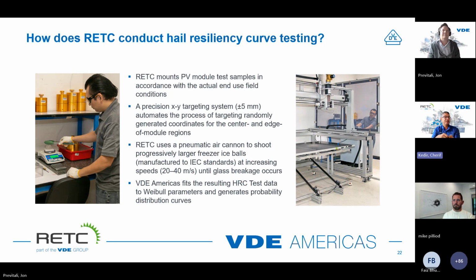And we do that, as JP noted, by increasing the ice ball size or the velocity. So we impact the modules using a pneumatic cannon. We make ice. We mold it into very accurate spheres. We measure it right before impact, so we know exactly the mass. We measure the diameter, and then we measure the velocity with lasers, so we know exactly the kinetic energy upon impact. That's actually measured, and it's really good. It's very repeatable. So that's how we are able to contain a lot of these variables in our testing.